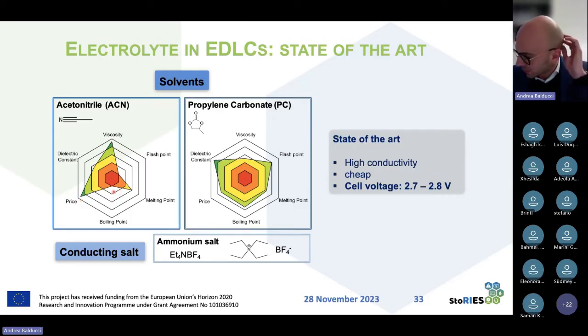And the advantage of using acetonitrile is that it gives us the possibility to have an electrolytic solution which displays high conductivity, also at very low temperature. So acetonitrile systems work very well also, for example, at -20 degrees, they are cheap, and they can be produced on a large scale. And when we use this solvent and this salt, which is the electrolyte, in combination with this system, as I mentioned before, we can then reach potentials of 2.7, 2.8, very recently even 3 volts, which is a very high cell voltage for these systems already.